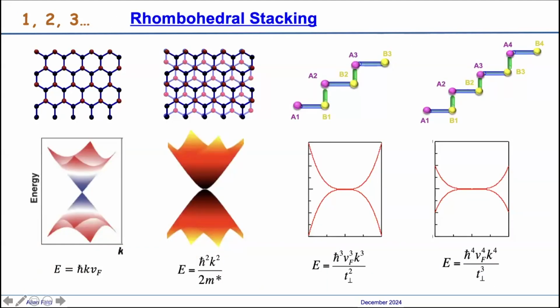So this is rhombohedral stacking. If you stack up graphene layer by layer with rhombohedral graphene, then, as Fan mentioned yesterday, the stacked atoms hybridize to form high energy orbitals. So basically we are left with sublattice A from the first layer and sublattice B from the top layer. As a result, the dispersion of this few-layer graphene goes as momentum to the power n, where n is the number of layers. So in 3 layers and 4 layers, this is cubic and quartic dispersion.